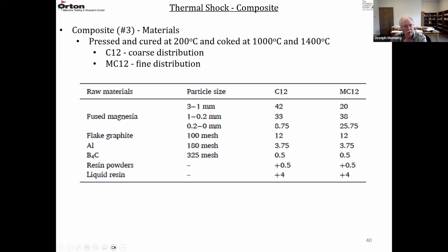They used fused magnesia. So this is a dense, low porosity magnesia at 3 different particle sizes: 3 to 1 millimeter, 1 to 0.2 millimeters, and 0.2 to 0 millimeters. The flake graphite was 100 mesh. They added an aluminum metal as an oxygen getter, an antioxidation agent. They also added B4C. That's also an antioxidation agent. It works a little differently than the metallic antioxidation agents.